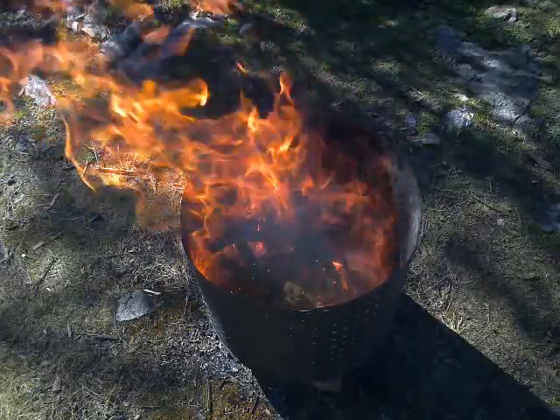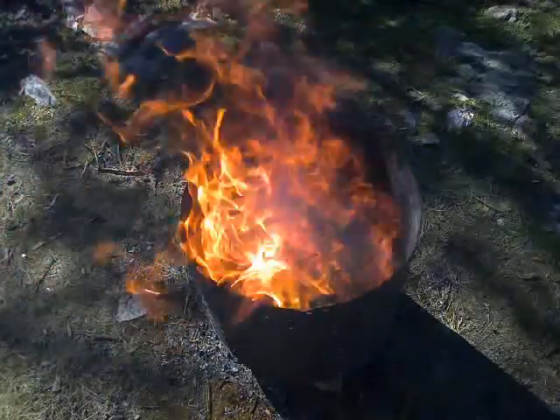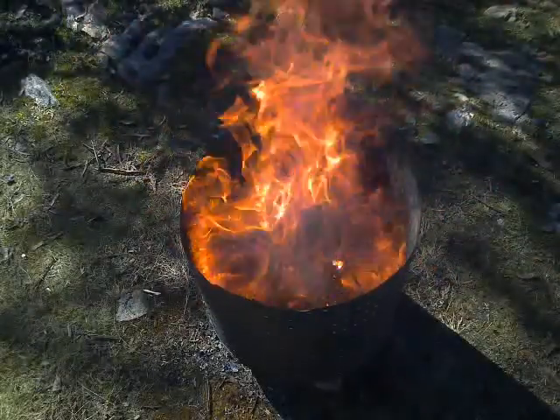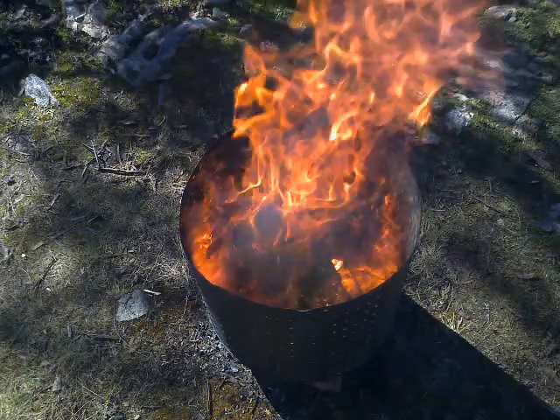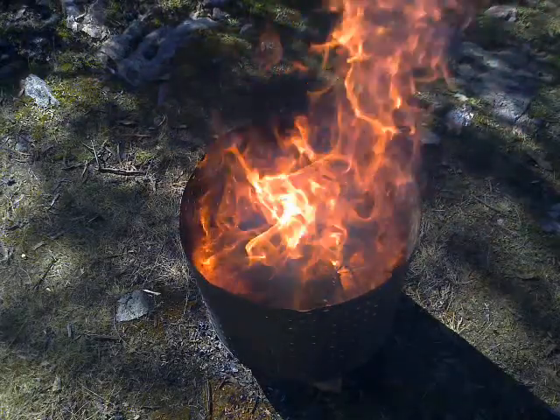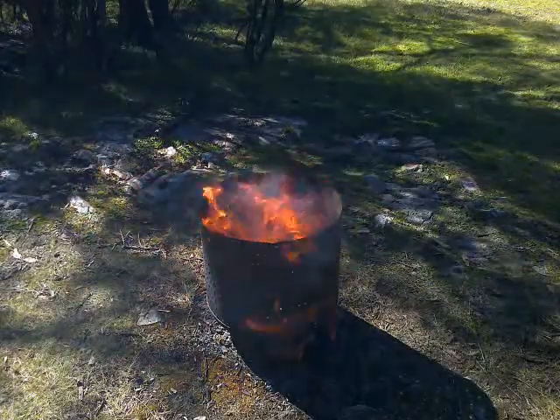And you will notice it resisted the fire for about 2.5 minutes. At 2.5 minutes, the edge caught alight. At probably 3.5 minutes, it started to separate and bubble and get going. And the first thing to catch alight was the glue, the adhesive. And that's still a really fuel-rich fire coming out of the burner can. I suppose, to prove the point, I'll put another bit in.